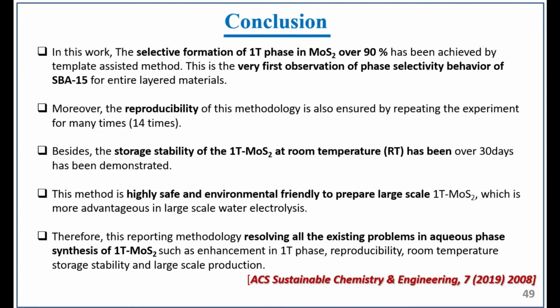So this work selectively forms 1T MoS2 inside the SBA-15. It forms 90% 1T MoS2. We produced the material over 14 times in our laboratory. We repeated the same experiment with the same quantity of material, and it produces reproducible data. Now the storage stability of 1T MoS2 at room temperature: we tested for 30 days, and it has very good activity and stability.